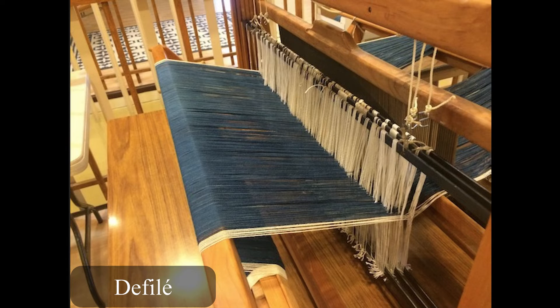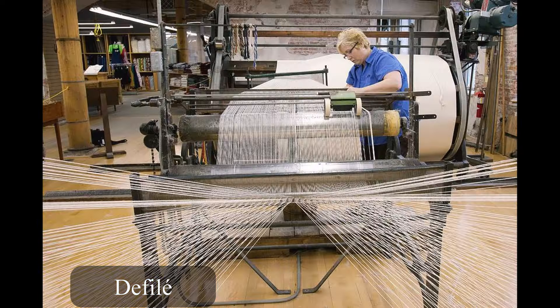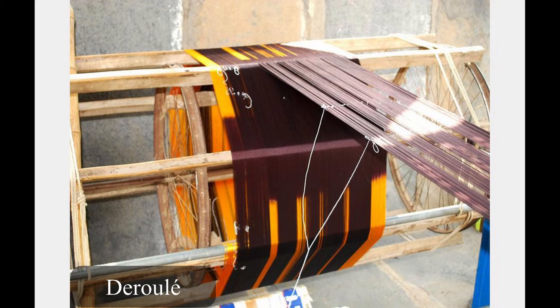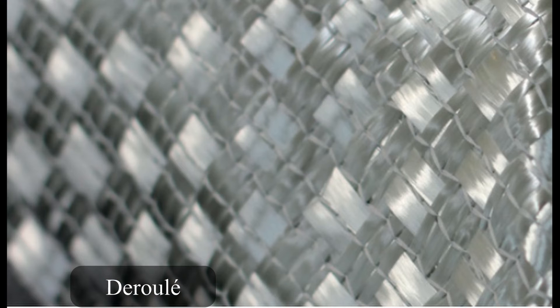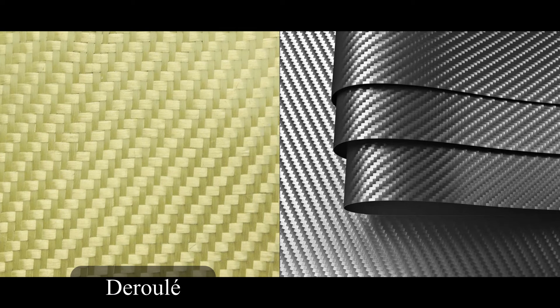You must be very, very patient if you want to warp the yarns, because you have to pass each single yarn through each hole — it's not an easy process. Warpers can be défilé and déroulé: défilé in the case of conventional yarns, and déroulé in the case of flat plates. These warpers must keep the strap horizontally without making it flex on itself. Glass fibers, aramid fibers, cut plastic films, and carbon fibers are warped like this.